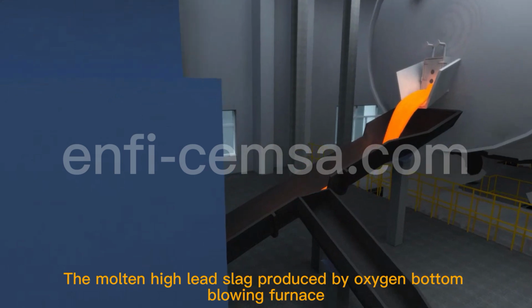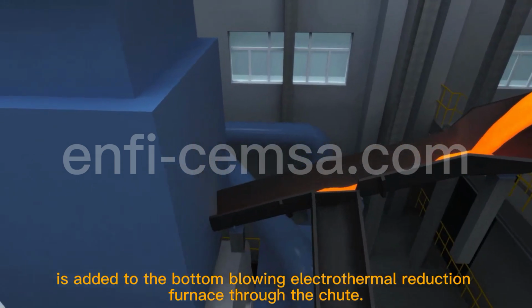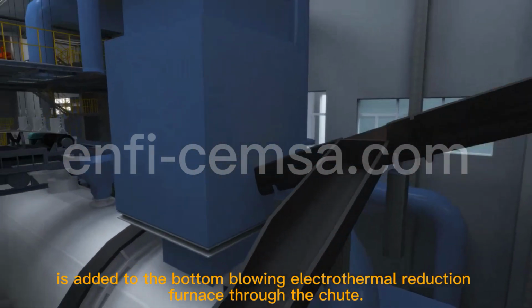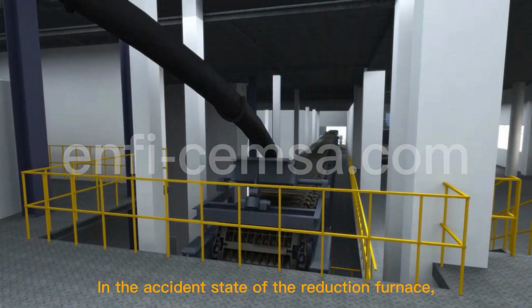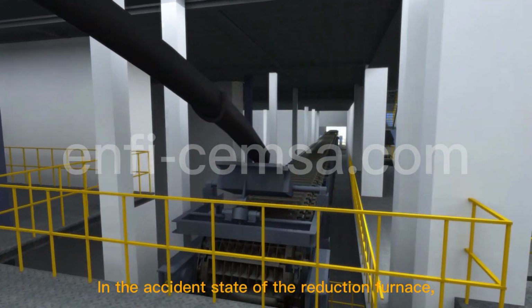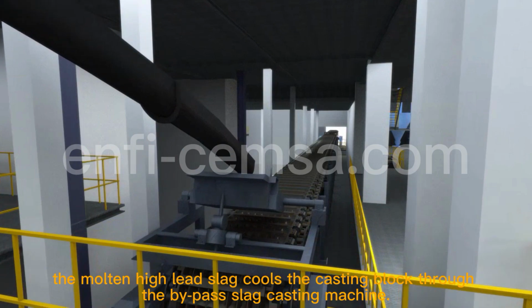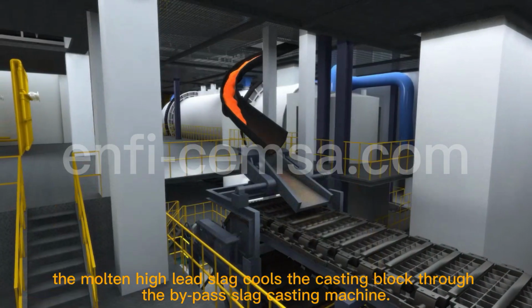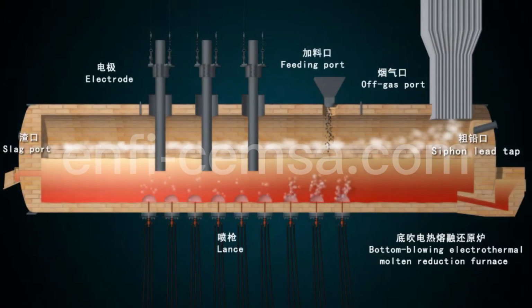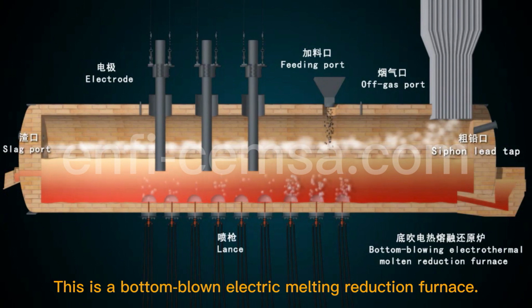The molten high lead slag produced by the oxygen bottom blowing furnace is added to the bottom blowing electro-thermal reduction furnace through the chute. In the accident state of the reduction furnace, the molten high lead slag is cooled and cast into blocks through the bypass slag casting machine.